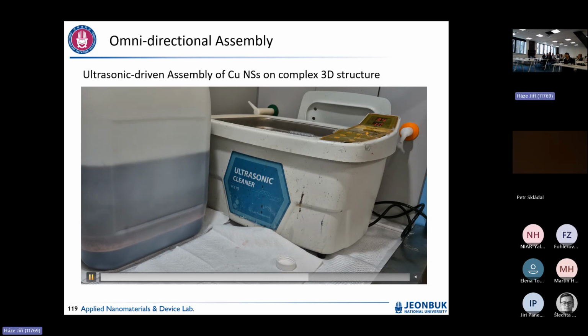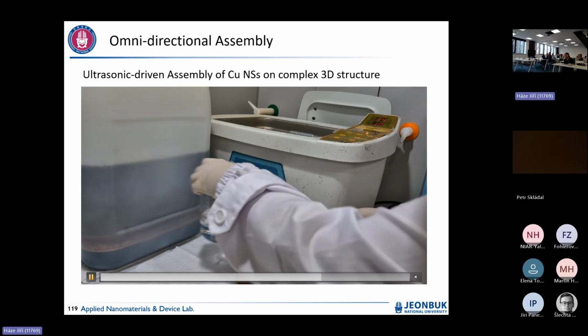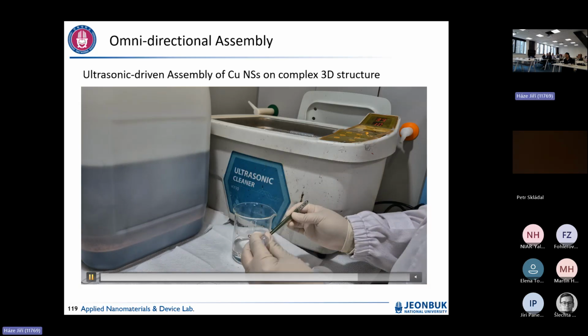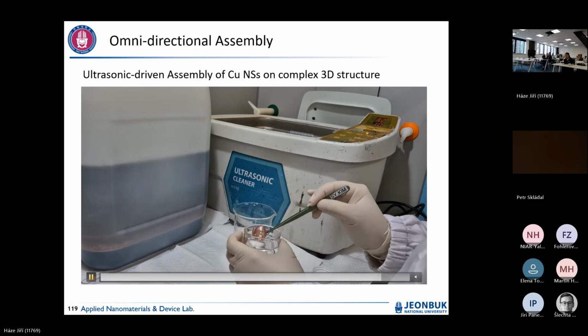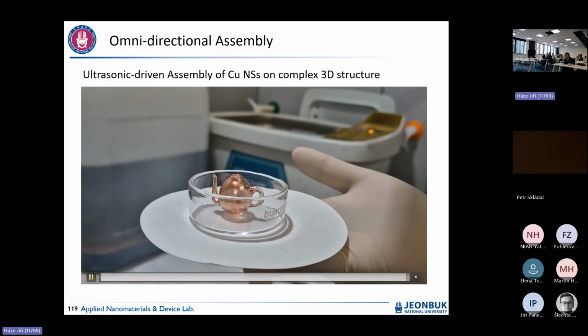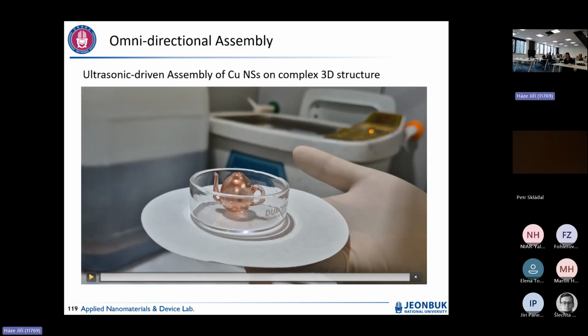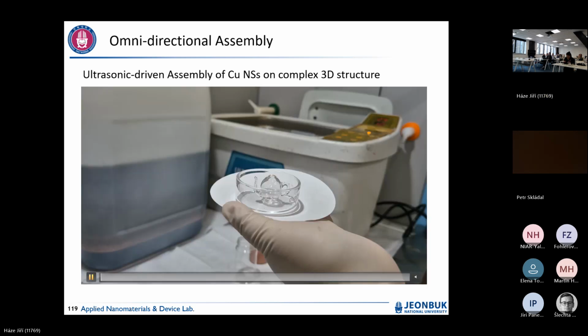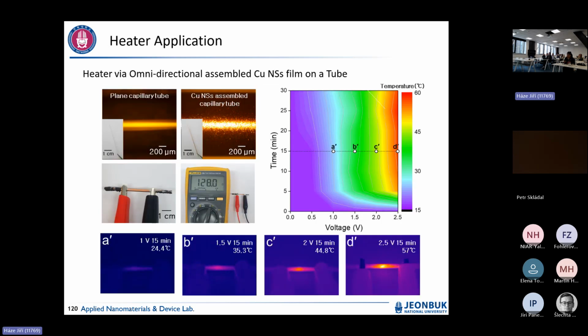And finally, we can get a really nice coating on the surface. It is applicable not only to the surface, but inside and outside, both sides are okay. And we tested heating. We used this one on the tube, then applied some voltage across it, so we can make a heater, a tube-type heater.